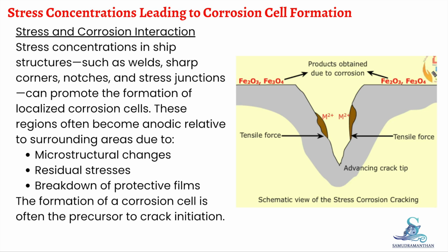Stress concentrations in ship structures, such as welds, sharp corners, notches, and stress junctions, can promote the formation of localized corrosion cells. These regions often become anodic relative to surrounding areas due to microstructural changes, residual stresses, and breakdown of protective films. The formation of a corrosion cell in such locations is often the precursor to crack initiation.